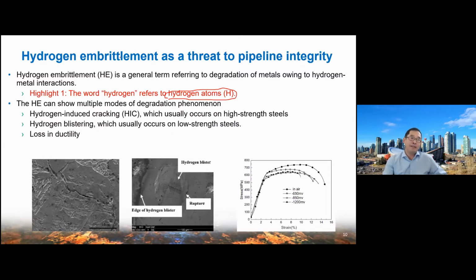After hydrogen embrittlement happens, usually it can show multiple modes of metal degradation. So hydrogen can cause cracking. We call it HIC. You can see the bottom picture on the left side, a sharp crack developed through the metal and can fail the structure. Hydrogen-induced cracking usually happens on high-strength steels. The second mode is hydrogen blistering. Hydrogen and hydrogen combine together to form hydrogen bubbles, hydrogen gas, increasing the local pressure to cause blistering of the steel. This usually happens on low-strength steels. The third one is very common, and you can see from the stress-strain curve at the bottom right side, it can cause the loss in ductility and elongation.